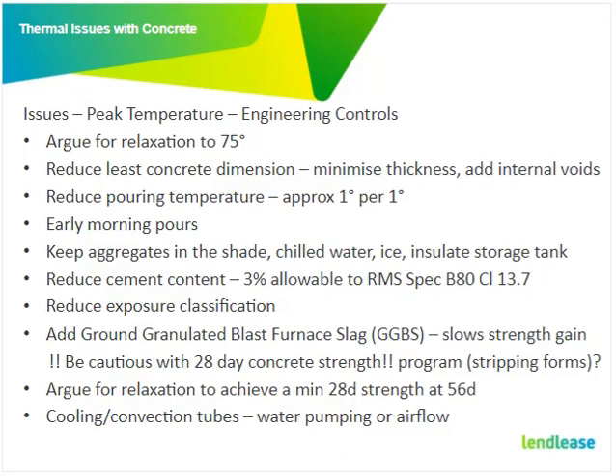There's another trick in the spec. You can reduce your cement content by 3%. So that was another thing we did to get under that 80 degree limit on Nambucca. Just applied that directly. Reduce your exposure classification. Let the engineers do their job. Let the durability engineers do their assessments and define the exposure classification. Don't just max it up because you think you're going to get a better durable outcome. It just doesn't result in that.